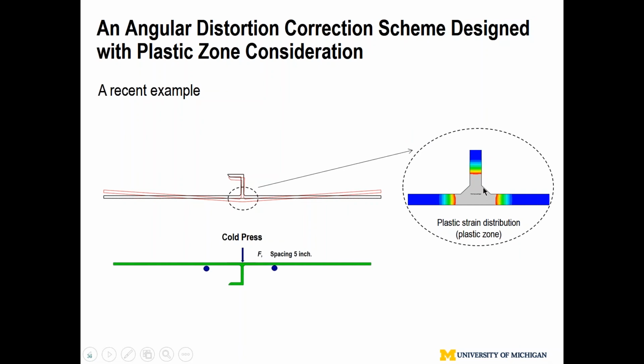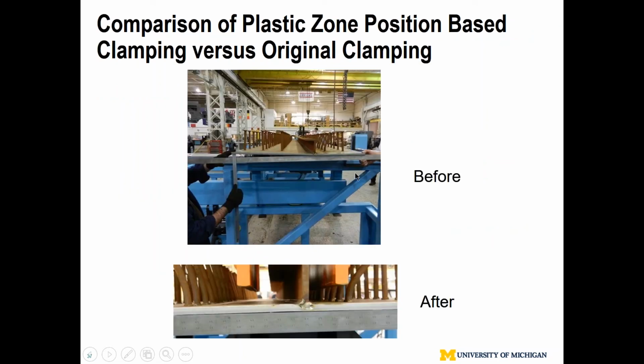The reason you want to clamp close, look at the red color. This is a computer model. That means this part, just like when you open a door, there's a plastic hinge. That hinge serves as rotation. The rest of them is rigid body motion, and actually the action is located all in this yellow region. That means you want to clamp as close as you can to the gray area. Actually, this company, they got the idea, immediately implemented it, compared with the reference, and then they have a clamping spacing of about 5 inches to 6 inches. You can see virtually no angular distortion.